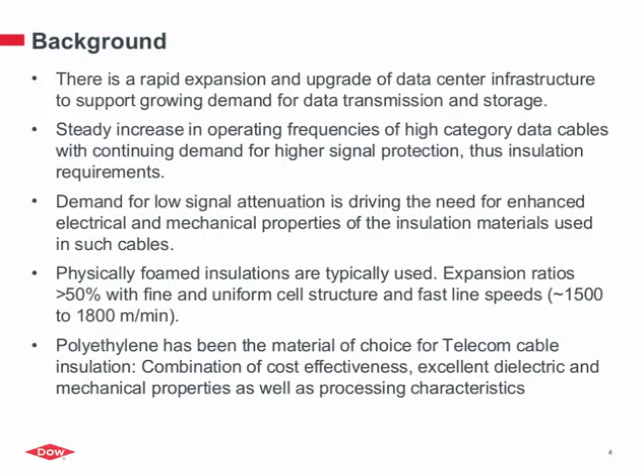And more also is the fact that these are produced at very high line speed. This is the extrusion speed at which these cables are made. It's about 1500 to 1800 meters per minute, depending on the manufacturer. That has a large demand on the design of the insulation itself from a processing standpoint. And polyethylene has been the material of choice for these telecom cables. It's because of a combination of cost. It's an effective way to insulate, and obviously excellent dielectric properties, as well as mechanical properties and processing speed.